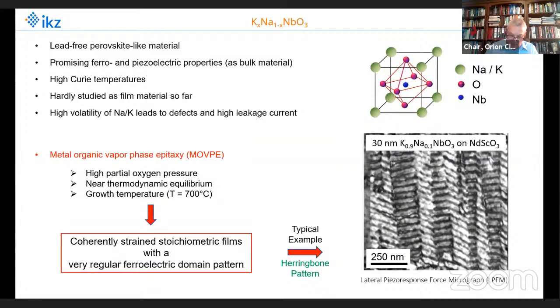And as a typical example, I show on the right side a lateral piezo response force micrograph of a 30 nanometer thin film grown on neodymium scandate substrate. And you see here a very regular herringbone domain pattern. And this high periodicity is a direct proof of the high perfectness of the thin film.